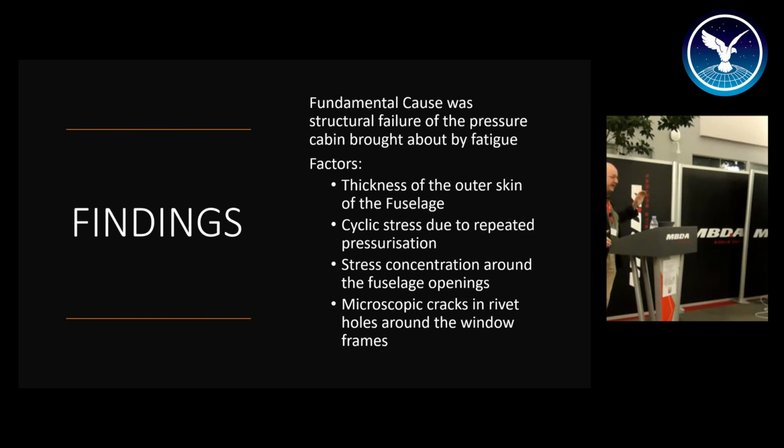They too were square. And when they got to the wreckage of YP up off the floor of the Med, they found that the part that failed was not a window. It was one of the hatches over the flight deck, which housed a radio aerial. And that was where the corner had cracked and caused the catastrophic failure. When they tested the sample aircraft in the water tank, it went at a window. When they did the earliest stress test, it had gone at a window. But the fact was that generally the openings are square, not specifically the windows.